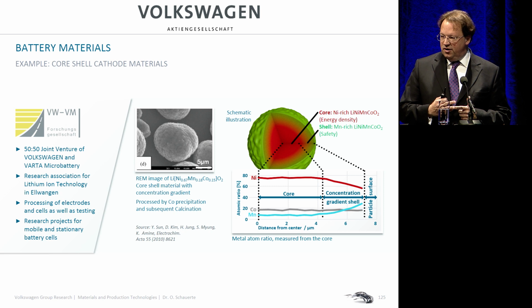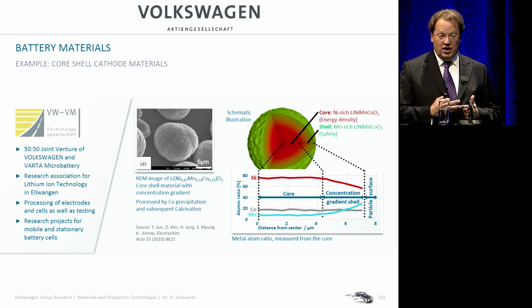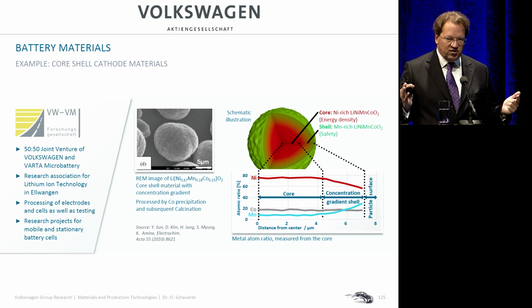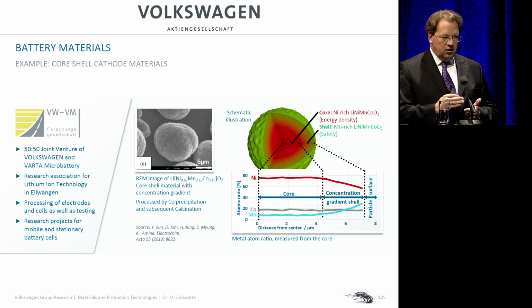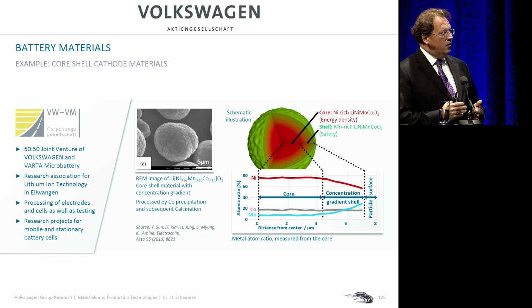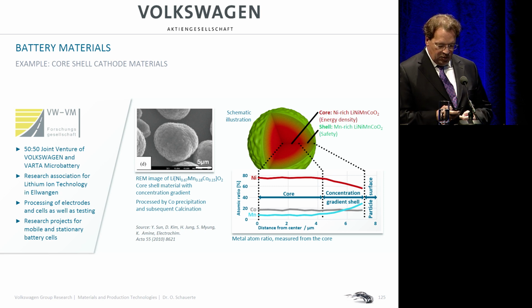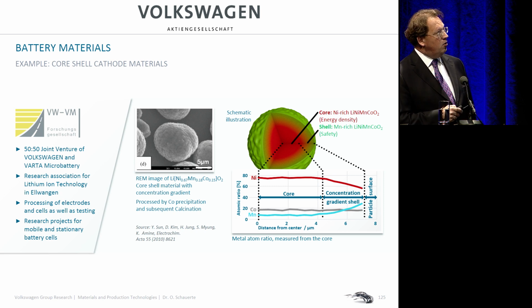So in case of an accident, if such a lithium-ion battery burns, you can't stop it burning. It will produce its own oxygen. It simply doesn't stop. To avoid this, which for safety reasons has the highest importance for Volkswagen, and I think for most others also, you reduce the electrical capacity of these materials by applying manganese and cobalt. So to overcome this problem, one approach for the future is completely new powders.